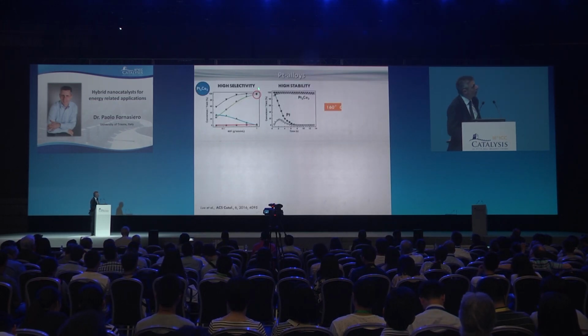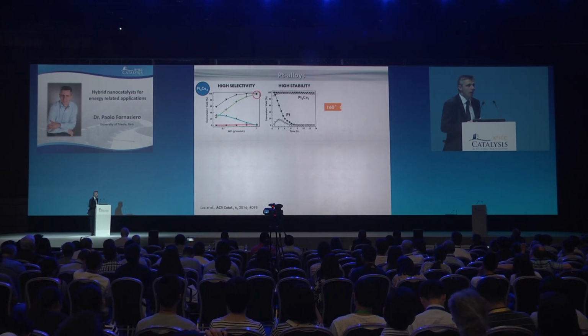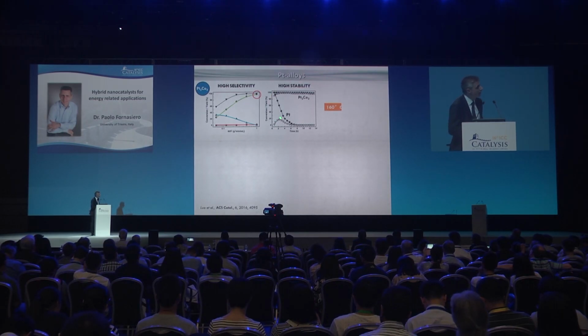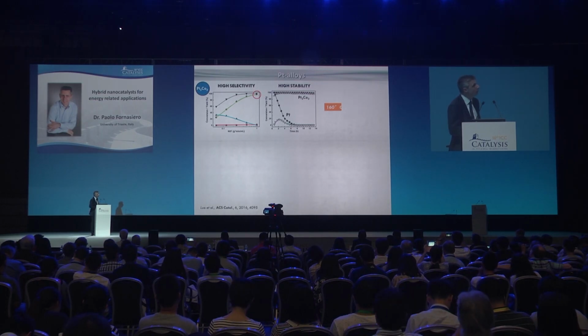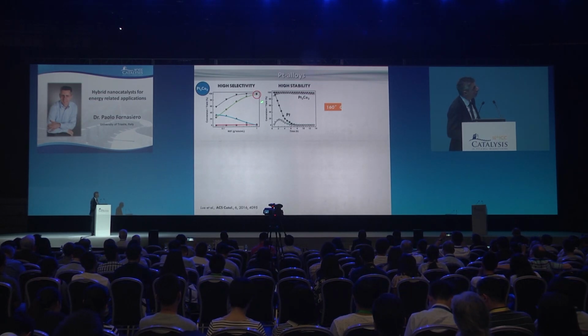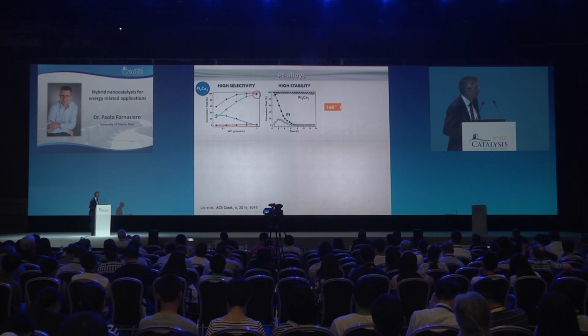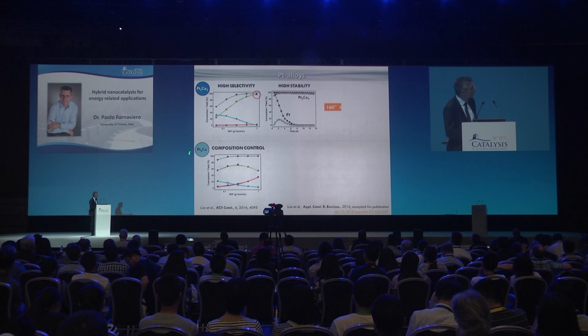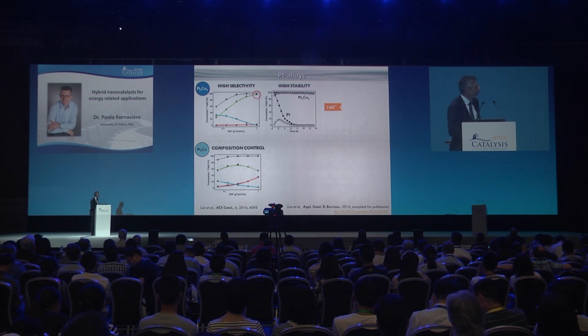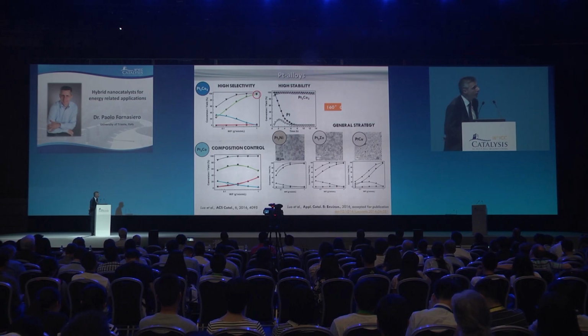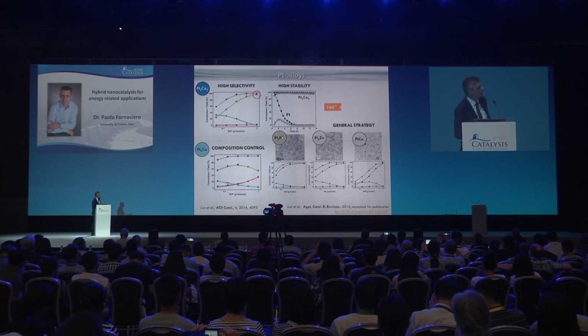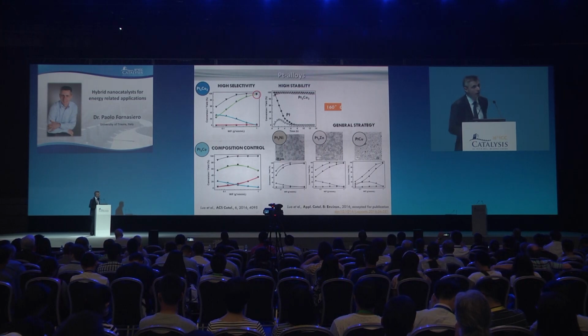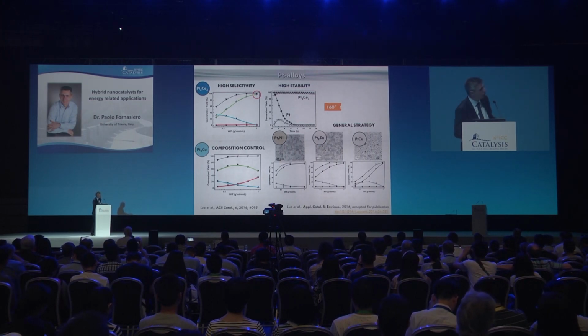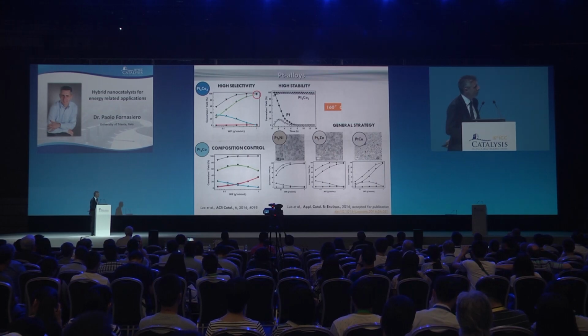And you do not just increase the selectivity here, but if you go higher in temperature, you also have an advantage in terms of stability. You see here the platinum deactivates within a few hours, while the activity of platinum-cobalt remains stable much longer. And you can also control the composition by playing with the platinum-cobalt ratio, and this approach is rather general. You can substitute cobalt with nickel, zinc, or copper. So there's plenty of room in this direction.